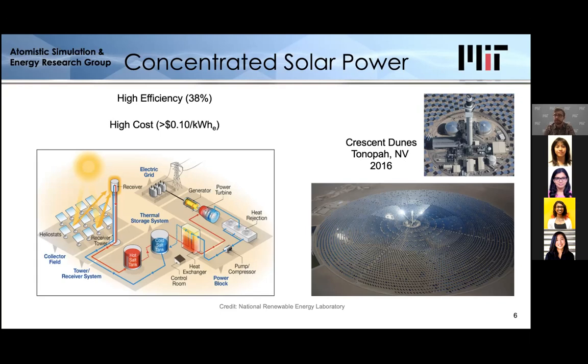The advantage of this system over other solar energy conversion technologies is that it can run at night. Basically, you heat the salt during the day, and then you can run continuously, outputting power all throughout the night. The conversion efficiency from heat to electricity, or rather from sunlight to electricity in this context, is also much higher. Efficiencies of 30 to 40% can be expected for this system rather than around 20% for a standard solar PV cell. Unfortunately, these systems are really unable to compete with PV cells these days in terms of cost.